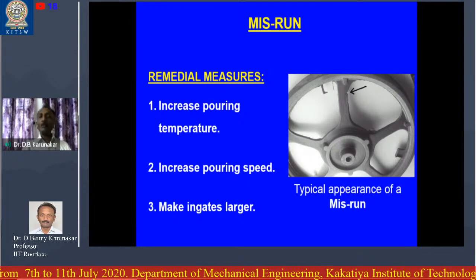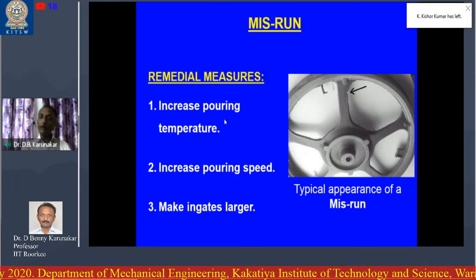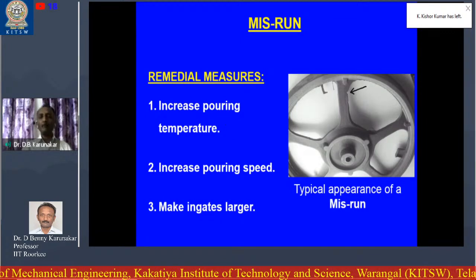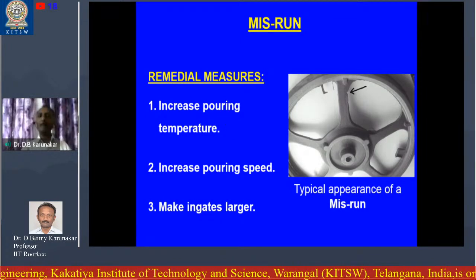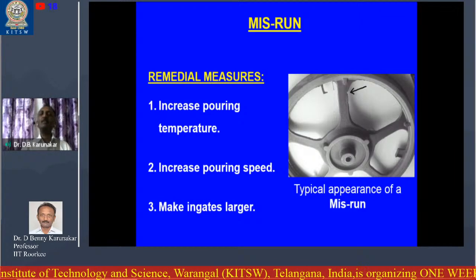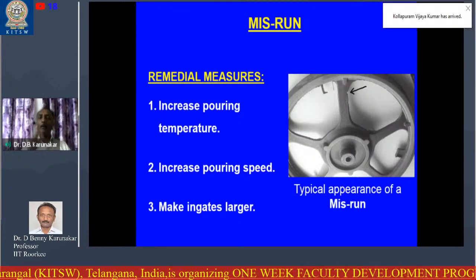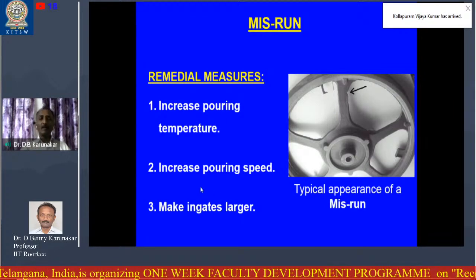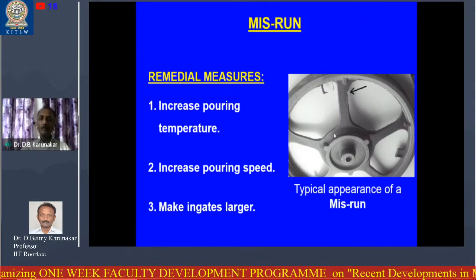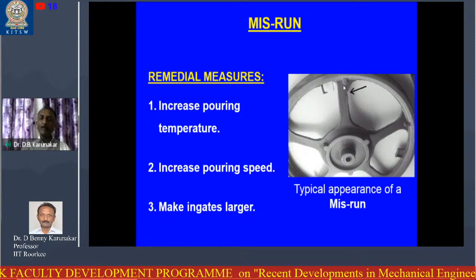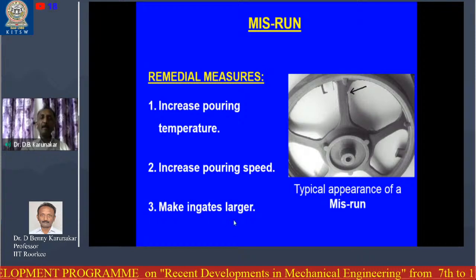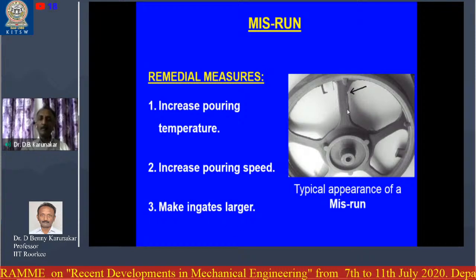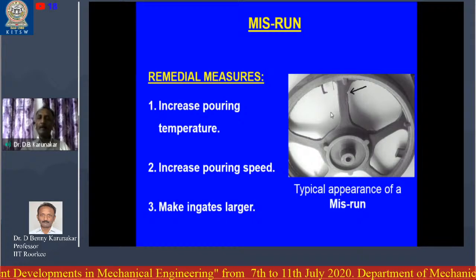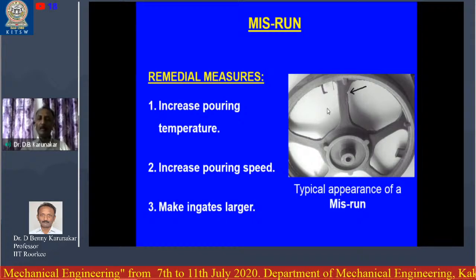As you increase the pouring temperature, what happens to the fluidity? The fluidity will be increasing and the viscosity will be decreasing. So the pouring temperature should be increased. Next, increase the pouring speed. That also will help us minimize this defect. Make ingates larger. With this we can minimize or prevent the misrun defect.